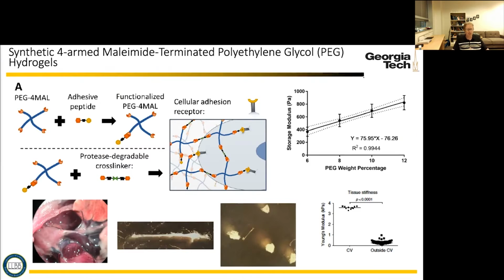engineered it. And the first thing he was interested in doing was targeting the tissue stiffness of native lymphatic tissue. And there was this one publication by Mika Frye when she was in Taija's lab, where she measured the stiffness right outside the cardinal vein, and this paper suggested stiffness could even be a cue to promote lymphatic migration, and that lymphatics prefer very soft tissues, and so we can make hydrogels right in this range of tissue stiffness.